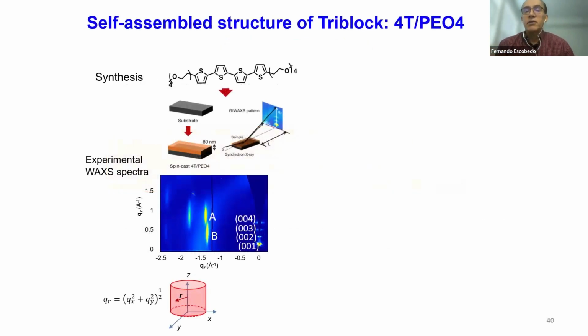So our collaborators synthesized and prepared these substrates, and then characterized them in different ways using microscopy, using thermal calorimetry, and of course using X-rays to try to understand what is the structure that you get in this substrate. This is illustrating a two-dimensional X-ray spectrum. So this QR will be basically the lateral signals, and the QZ will be the vertical in these layers.